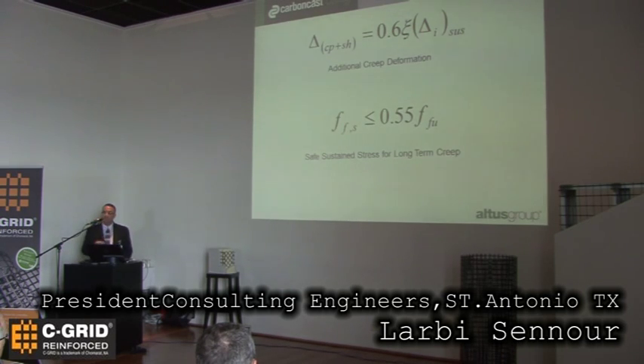Then if you have a sustained load, a load that's permanent, I'll give you an example. When you have a sandwich wall panel where your interior wythe is structural, you have the insulation and the exterior wythe, but the exterior is not grouted at the base. It's really hanging from your structural wythe. That load is sustained on the grid. And then for that grid, we usually use 0.55, right?